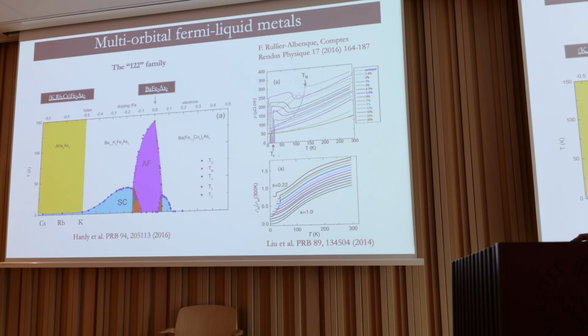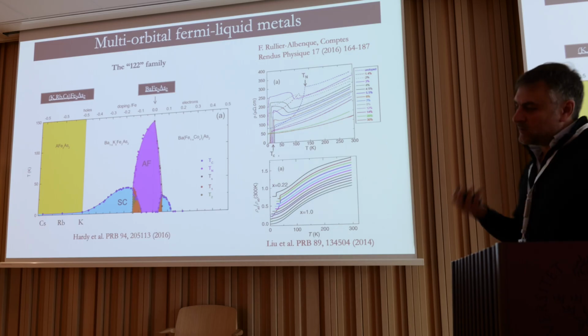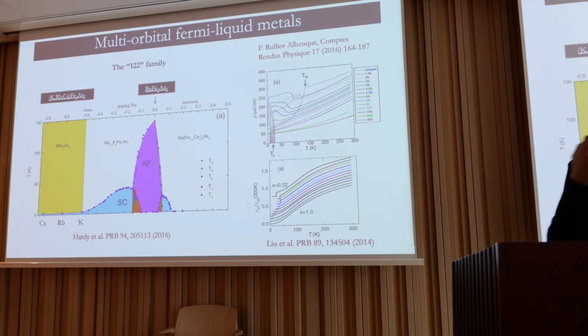So one of the family I like most is the 1-2-2 family. Most because what I try to highlight is that doping of the carriers in the plane is a super fun knob to play with, and the 1-2-2 family is the one that you can actually dope a lot, from the electron side to the hole doped side. Typically you dope electrons by putting cobalt instead of iron or other transition metals in the plane, and you put holes by putting, as you know, potassium instead of barium.